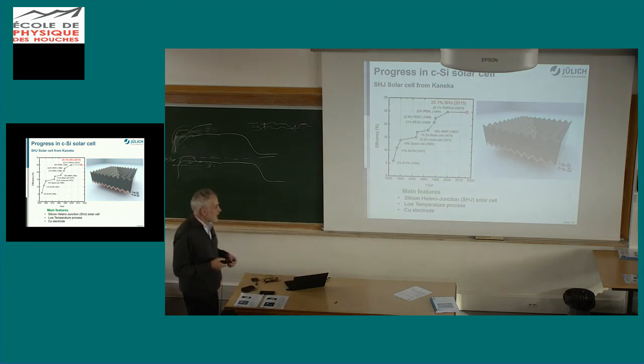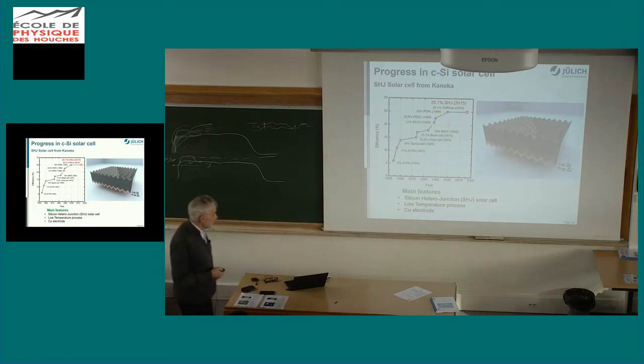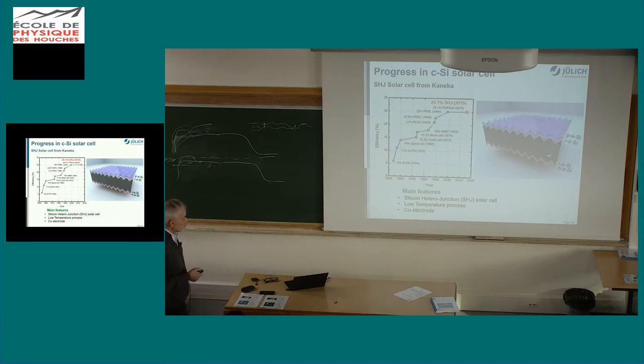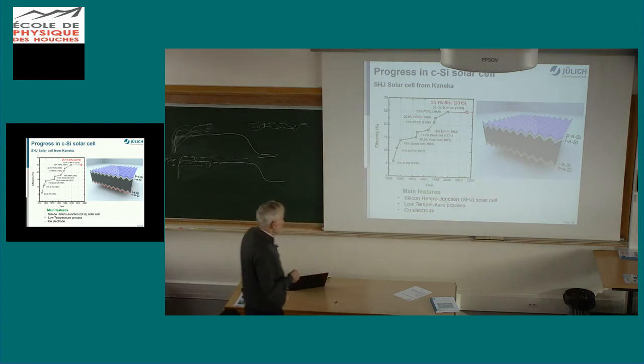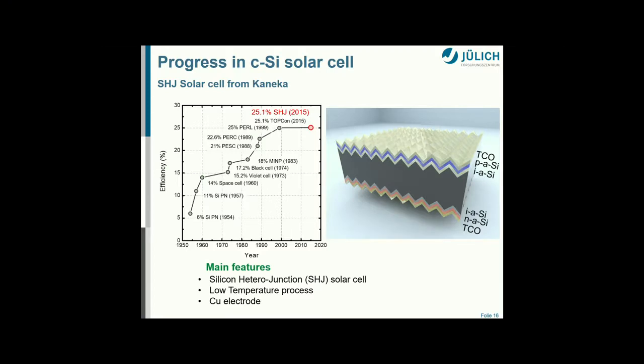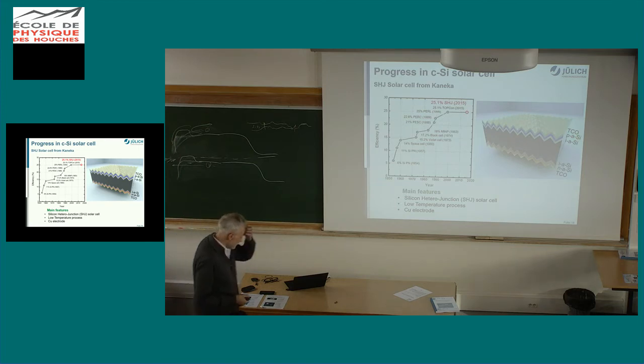The purer you are, the better your amorphous silicon is. And it's very clear that the surface passivation of the wafer can only be achieved if you have an undoped amorphous silicon. And that way you also do the PN junction. So starting here with an N wafer, you have on both sides this intrinsic passivation layer and the doped contact layer.